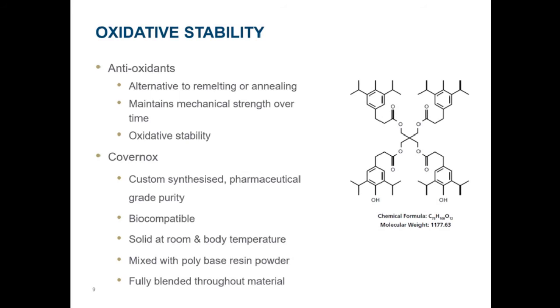The use of antioxidants is another way of eliminating free radicals, and they are used as alternatives to remelting or annealing. The evolution of this next generation is driven by the need to retain the crystalline properties while preserving the oxidative stability of the molecular chains upon irradiation. The doping agents used to date are antioxidants, which neutralize the free radicals created during gamma irradiation without the need for heat treatment. The elimination of heat treatment reduces the decrease in mechanical properties as seen with both remelting and annealing, while maintaining the good mechanical strength and wear properties of the polyethylene material.